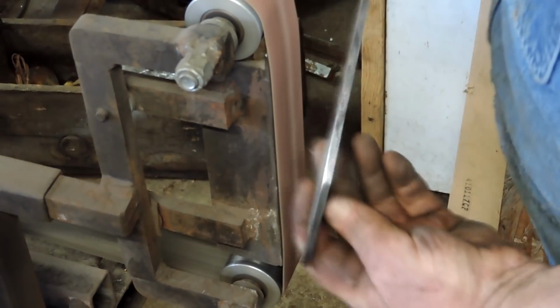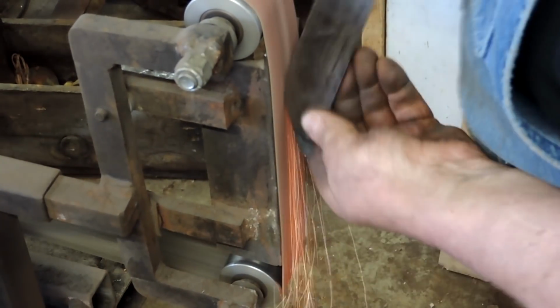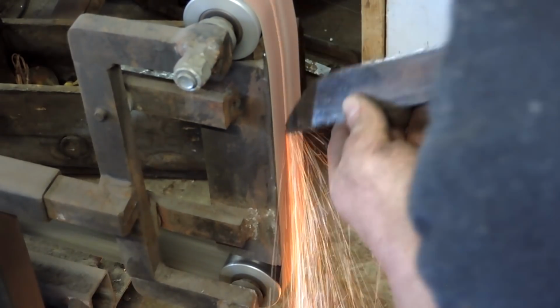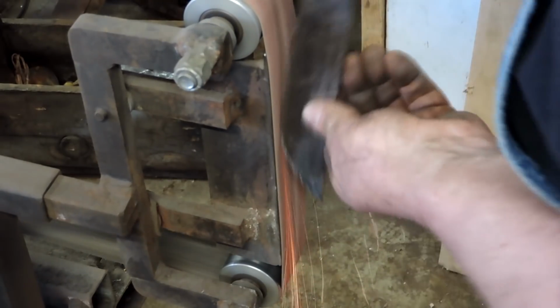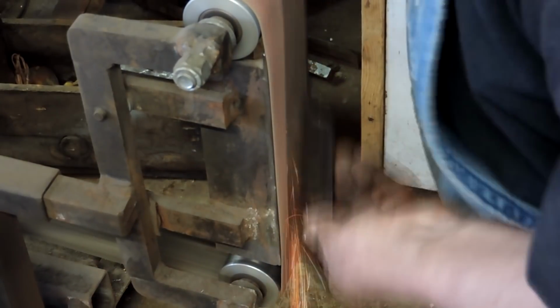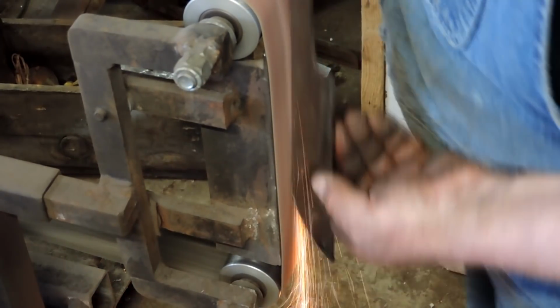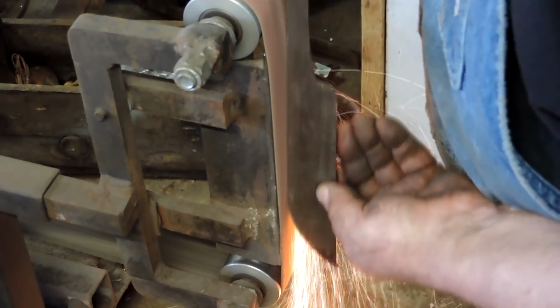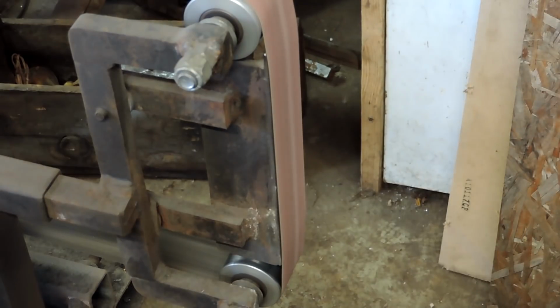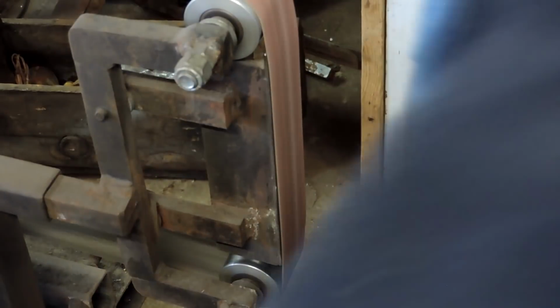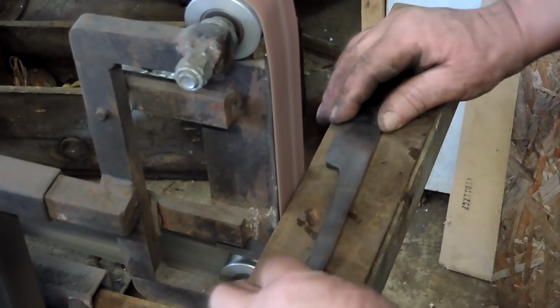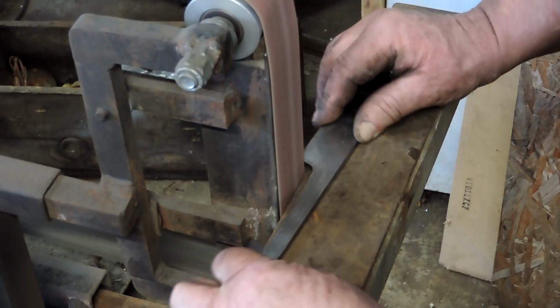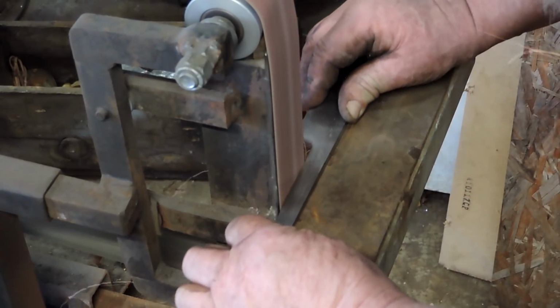Alright. So as far as the profile of this thing goes, I'm going to grind on the spine until I do not see any more cracks. And there are a few cracks in it that I can see. Looks like several of them forge welded together while we were cleaning up the billet after the press. But there are quite a few there. And where I cut the tip at an angle to forge that drop area in, there don't seem to be any cracks at all, so I don't believe any cracks go through the billet.